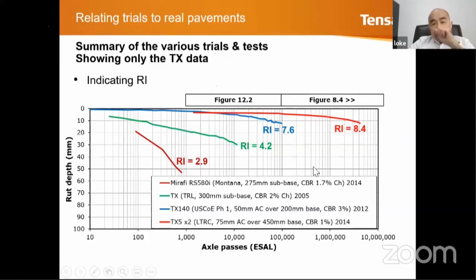We carried out another test, and this is with the Louisiana Transportation Research Center. And this is now going way beyond 100,000 passes, which is right here. What we have done here is a plate load test, and this is up to 4 million passes, and this is the real McCoy, if you like. This is where the real things are happening. The actual roads are around here, not here. You don't have a road whereby the number of passes of traffic vehicles is less than 1,000. And here you can see again, we have less than 15 millimeters of rutting.